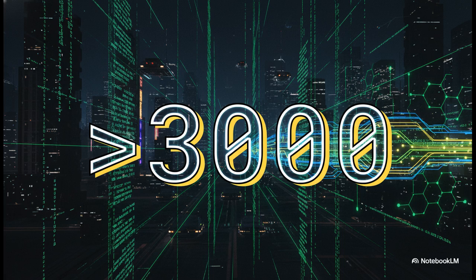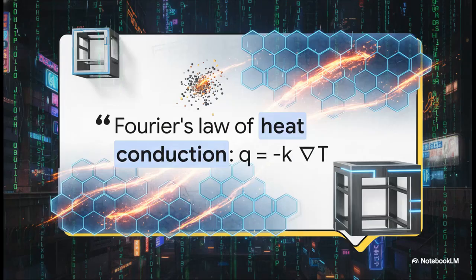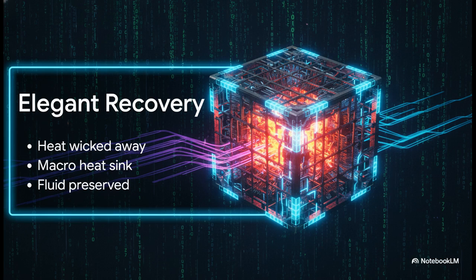And this is exactly where pristine graphene proves it is absolutely vital yet again. With a jaw-dropping thermal conductivity of greater than 3,000 watts per meter Kelvin, it acts as a molecular superhighway. It instantly grabs that intense, localized friction heat and pulls it away. We can actually model this brilliant thermal dissipation using Fourier's law of heat conduction. The heat flux density, Q, is governed by the temperature gradient and the incredibly high thermal conductivity of the graphene, which is K. Basically, this perfectly illustrates how the graphene serves as the ultimate bridge. It aggressively wicks the intense heat right away from the jammed nanoparticles and dumps it directly into the massive macroscopic aluminum scaffolding.